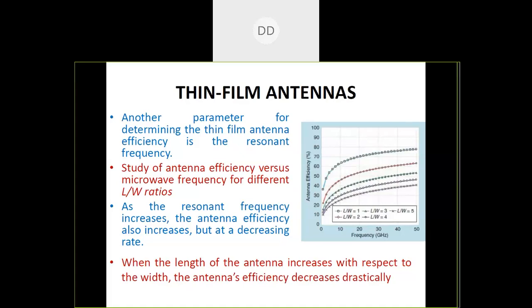But the increase in the efficiency is at a decreased rate, so it is not a very large or linear exponential increase. But the increase is there. When the length of the antenna increases with respect to width, that means the L by W ratio, the antenna efficiency decreases drastically. So the length to width ratio of the antenna is also an important parameter in designing optically transparent antennas. These are different parameters which we need to analyze when we want to use thin films for the design of optical